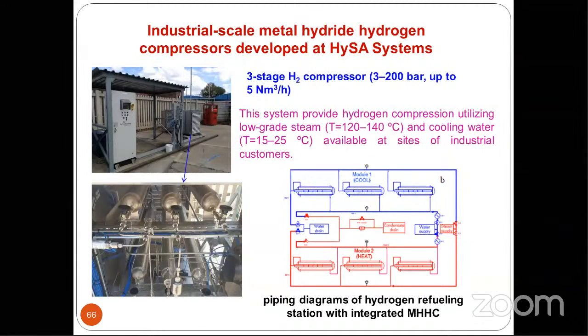Here we have developed the metal hydride compressor. It can compress hydrogen by taking some waste heat from industries. Suppose you have low grade waste heat at 120 to 140 degrees from industry. That heat is used as the driving force to compress the hydrogen using these metal hydrides. We have designed a 3-stage compressor, which can take input at 3 bar and deliver hydrogen at 200 bar, up to 5 Normal cubic meters per hour.